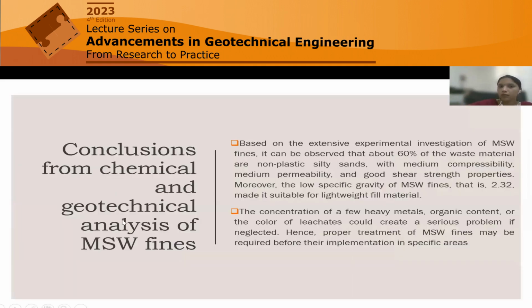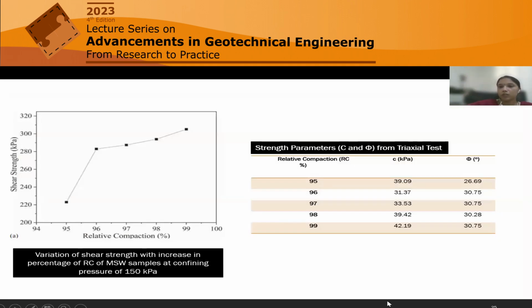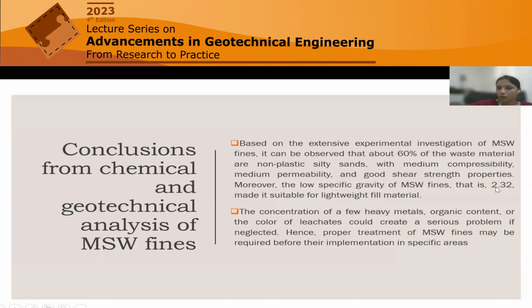Then the conclusion from chemical and geotechnical analysis: what we can say from this limited experimental study is that nearly 60% of the waste material is non-plastic silty sand, with medium compressibility and low to medium permeability, and it is giving us good shear strength properties, as you can see here. The specific gravity is quite low compared to soil, 2.32, which makes it suitable for lightweight fill material also. However, if you check the chemical characterization results, a few heavy metals like iron and titanium are present, and the organic content is also a little bit high. The color of the leachate could also create a serious problem if it percolates into the groundwater. Hence, we should recommend some proper treatment of this MSW, particularly this Varanasi MSW fines, before field implementation.